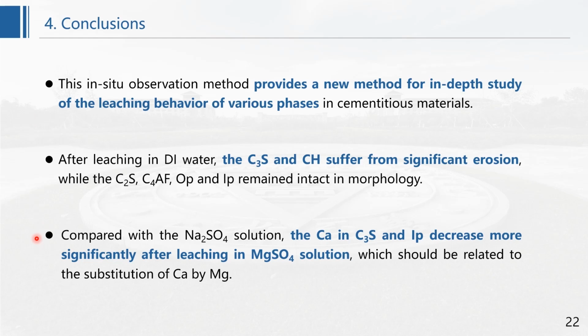Finally, compared with the sodium sulfate solution, the calcium in C3S and inner product decreased more significantly after leaching in magnesium sulfate solution, which should be related to the substitution of calcium by magnesium. That's all about my presentation.